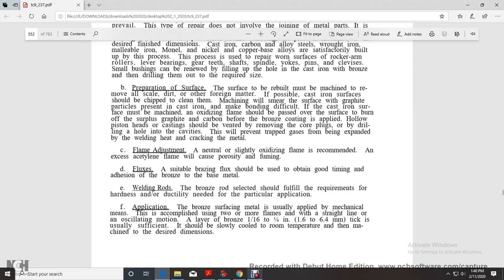A hollow piston head casting should be vented by removing the core plugs and drilling holes in the cavities. This will prevent trapped gases from expanding during welding, heating, and cracking the metal. Alright, flame adjustment. A neutral, slightly oxidizing flame is recommended, but an excess acetylene flame will cause porosity and fuming.